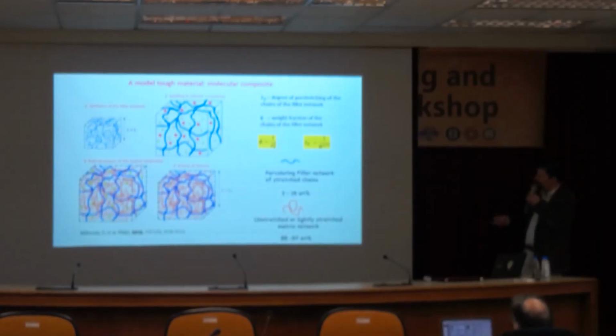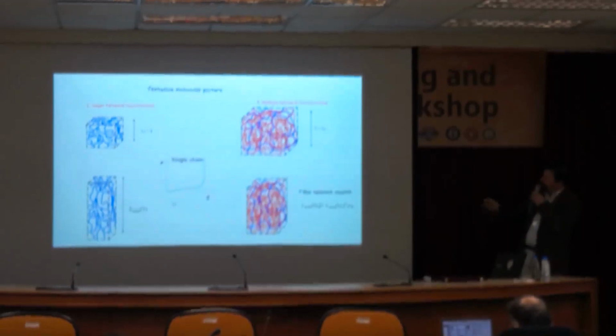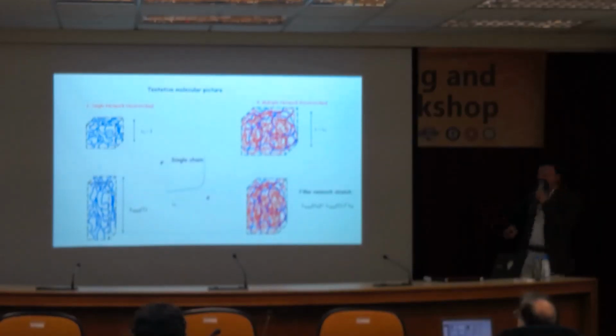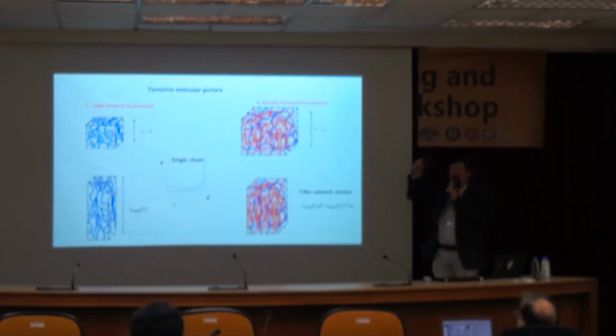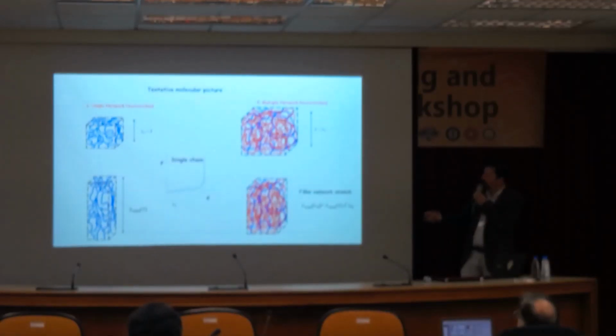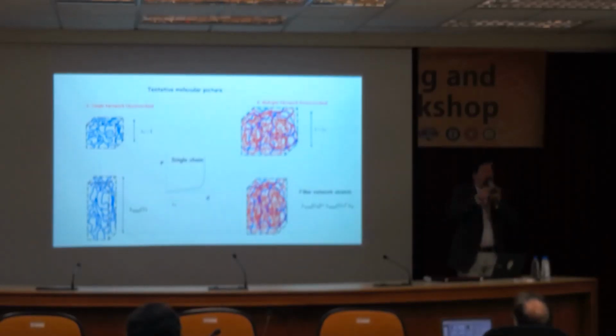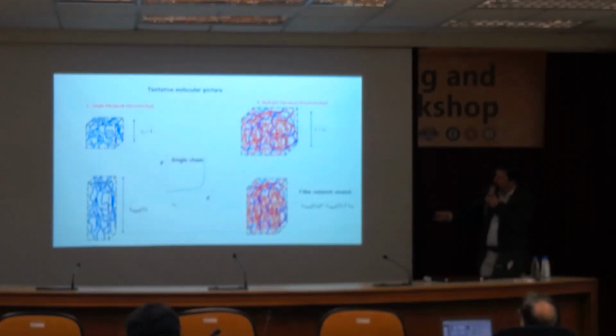So most of the material is this unstretched or lightly stretched matrix network, and this is the filler network. The way it works is that, if you're a polymer chemist, you would think that if you stretch it all the way to the point where the chains forming the mesh are fully stretched to their average length, you get to the maximum extensibility of your material. If you look at the single molecule, initially you have entropic elasticity, then enthalpic, and you get to strain hardening and breakage. So in principle it should do that, but in reality this material will break at a much lower extension for crack propagation.